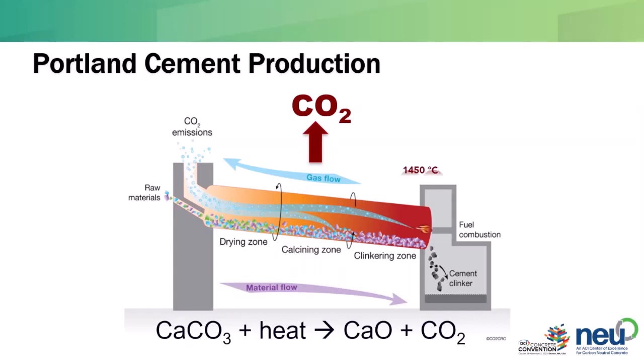In addition, those materials inside that kiln need to get to roughly 1,450 degrees C, which is very hot. So we're burning a lot of fuel in order to keep that flame at the temperature it needs to be. So those are the two primary producers of CO2, or the two primary activities, I guess, that are responsible for that carbon footprint.